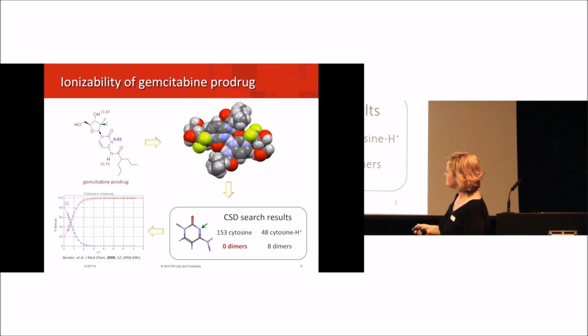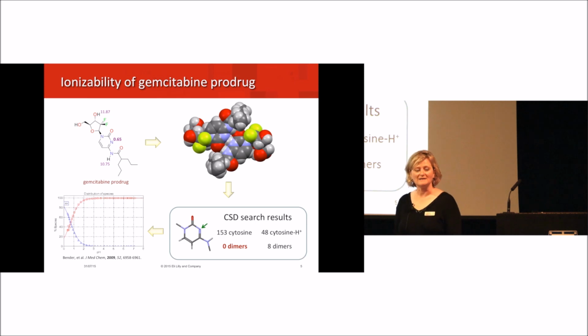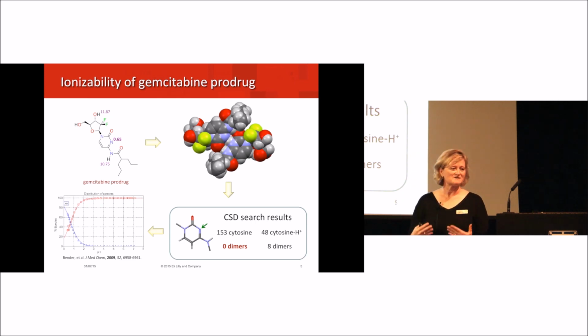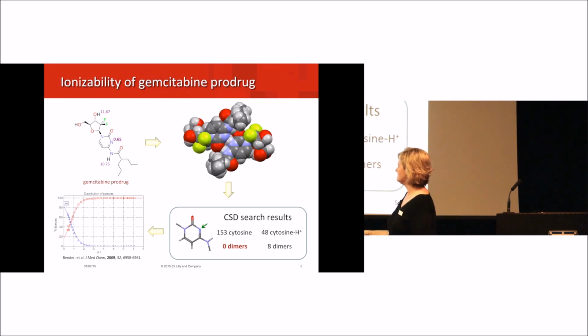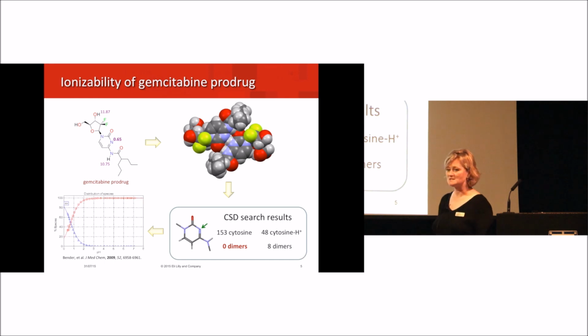It also caused our organization to go back and reevaluate and change the methodology for measuring pKa's, and in fact there was a pKa at a very low pH. And this sort of information is great from a scientific standpoint. You want to be right in the data that you're correcting. But there are also practical ramifications for this. Some may argue, well, this is outside the physiological pH range. But the reality is this actually helped us understand some of the pH instability that we had with this compound, recognizing that it was ionizable.